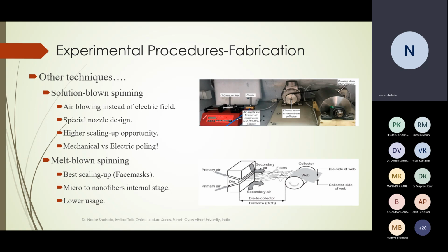There is one last example here about fabrication techniques related to melt-blown spinning. This one is traditional in the fabrication of face masks because of its high scaling up opportunities compared to the previous techniques. However, it has some drawbacks in the formation of nanofibers from the microfiber level, because most likely this technique forms microfibers first, and then by time it could be converted into nanofibers. So in the case of generation of nanofibers, it's relatively less used compared to solution blowing and electrospinning for PVDF nanofibers. But if you would like to fabricate PVDF microfibers or PVDF cast film, in this case, melt-blown spinning could be your optimum choice.